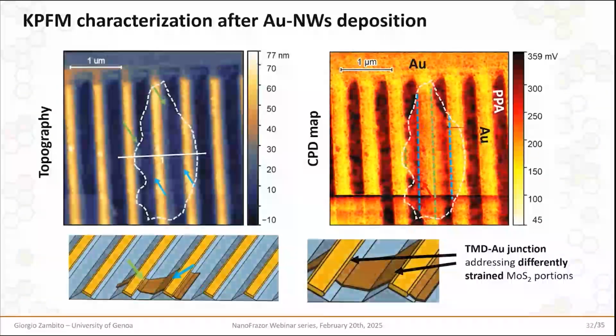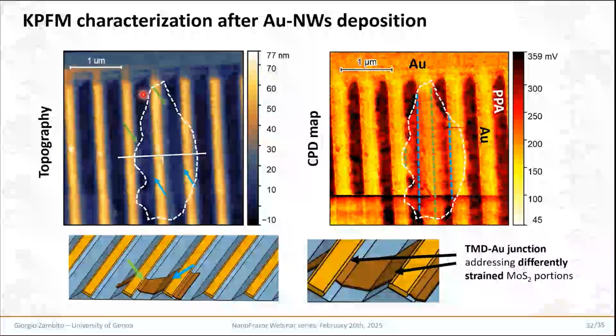And if we observe again this configuration after gold nanowire deposition, we observe, again by Kelvin probe force microscopy, this confinement of gold, which we see from the topography image, but even more clearly from the CPD map. And here you see the periodic modulation of work function that is given by the alternation of gold nanowires and exposed PPA, which is represented by these darker regions.